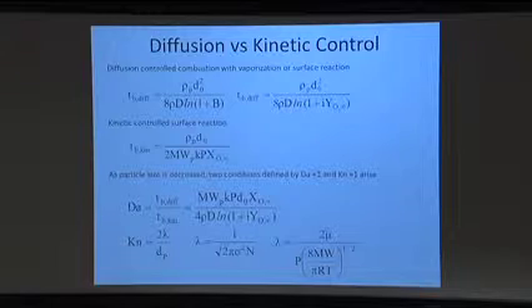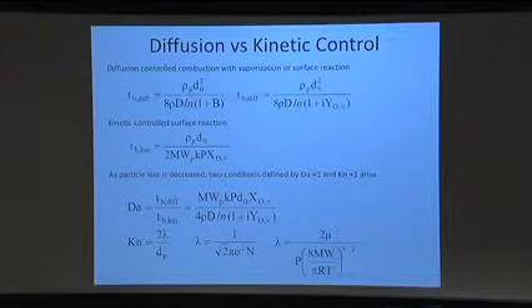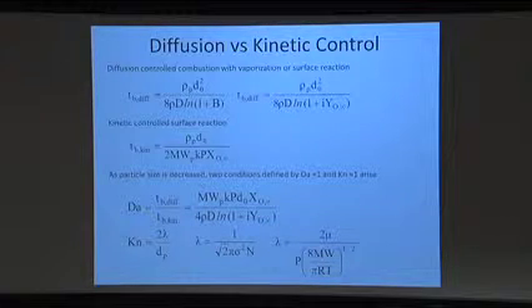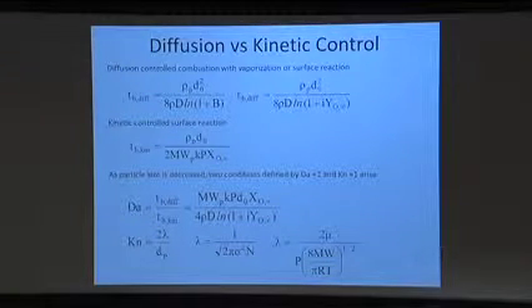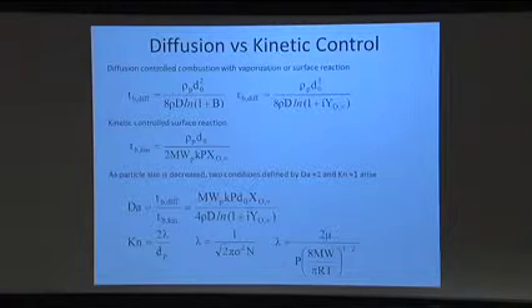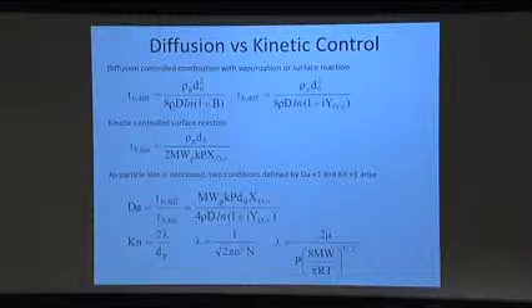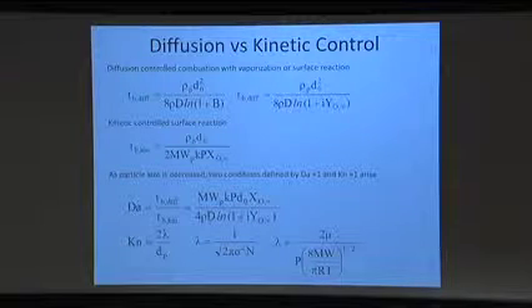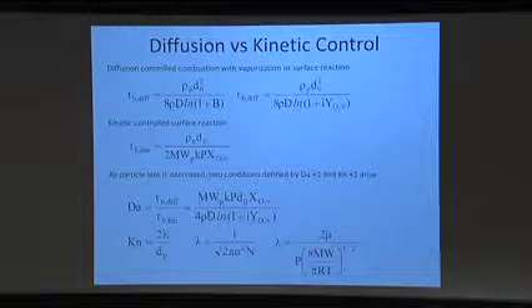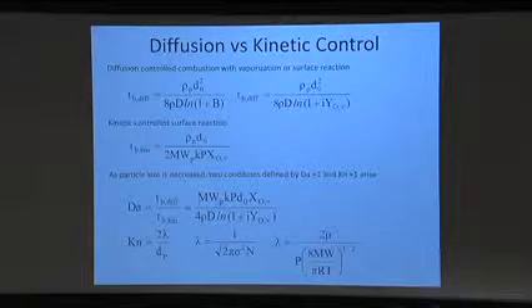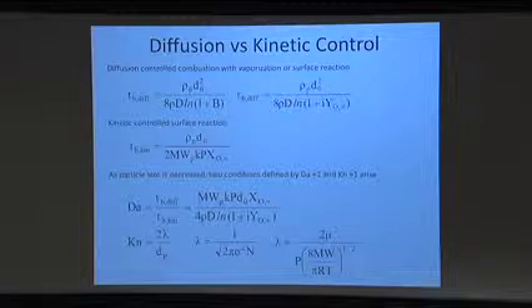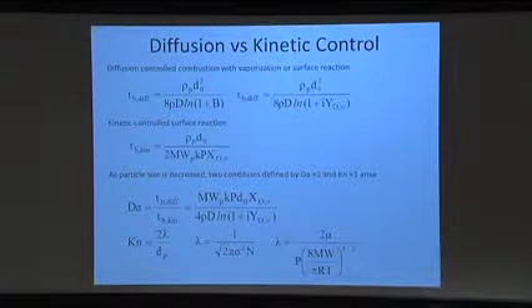Okay, if you do a back of the hand calculation and you assume I'm starting with a particle of about 100 nanometers, 1/10 of a micron, what you find is you have Knudsen numbers greater than 1 for the entire temperature regime relevant to combustion, from room temperature all the way up to typical flame temperatures. So for 100 nanometer particles and smaller, I'm starting to get into this regime where I've got to start asking myself, is Fick's law, which is describing this mass transport on a continuum basis, is that still valid or not?